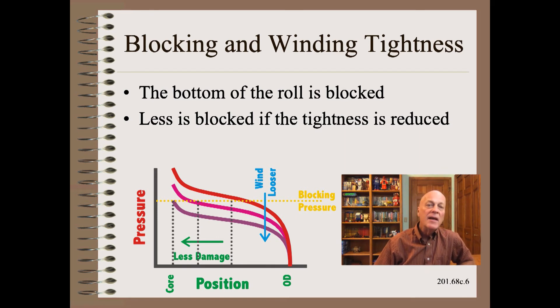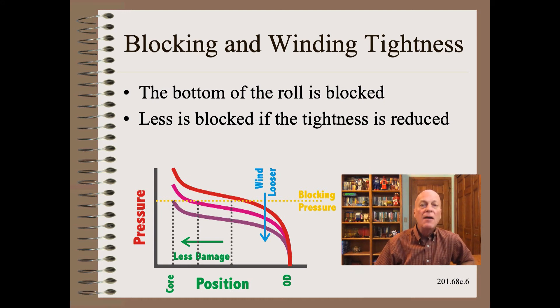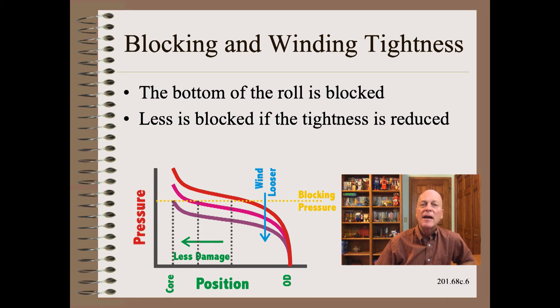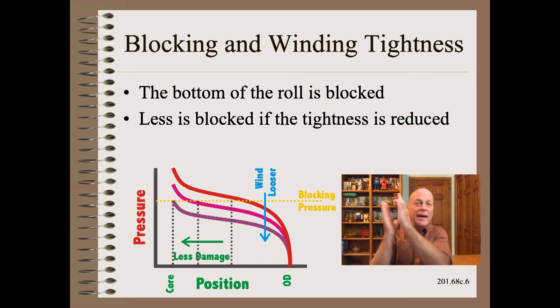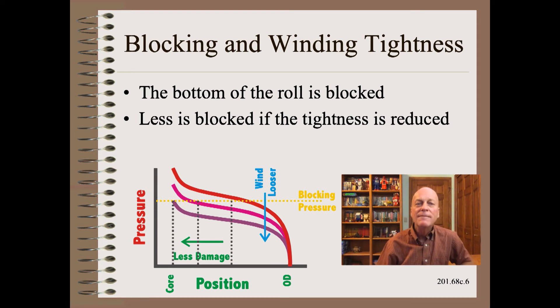The purple, magenta, and red lines indicate a reasonable range of winding tightness achievable in the real world. If you wind tight, as shown in red, the bottom half of the roll is unacceptably blocked. If you wind normally, only the material very near the core is lost. Finally, if you wind painfully loose — so loose that you might get nearly unshippable egg-shaped and flat tire rolls — you might save all of the roll from blocking. The winder saves the day: no more blocking, only just a few loose roll complaints in its place.